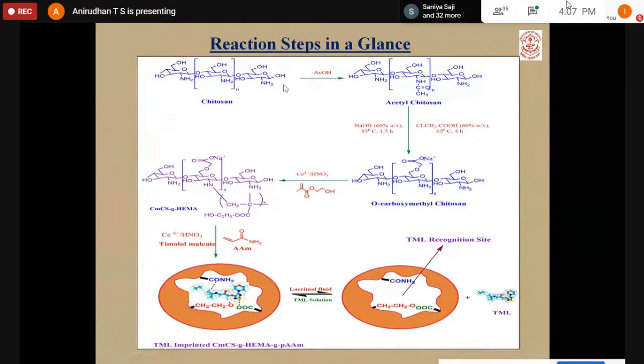So this is chitosan, a polysaccharide. Acetyl chitosan is prepared, then treated with chloroacetic acid. We have introduced a COOH group, and finally reacted with hydroxyethyl methacrylate, another monomer, and we have introduced polymerization, and we have a molecularly imprinted polymer with your template. Here the template is the anti-glaucoma drug timolol maleate, and this is the drug that we have introduced. You see the drug, this is the drug that we have introduced in the cavity of this material, and we leach out this drug in lacrimal fluid, so that we create an imprint, and this is the TML.